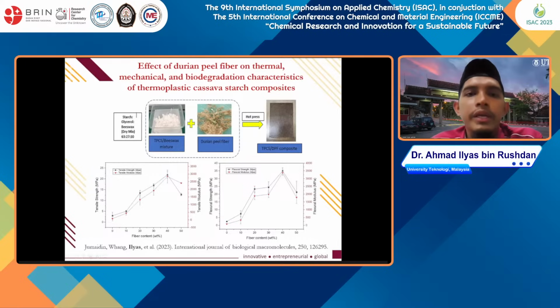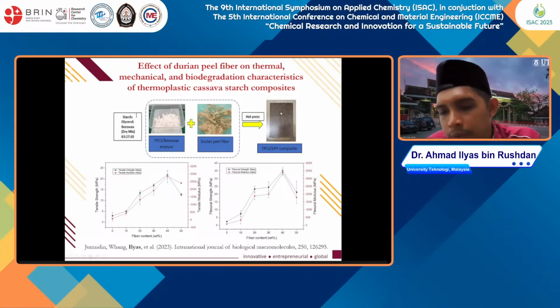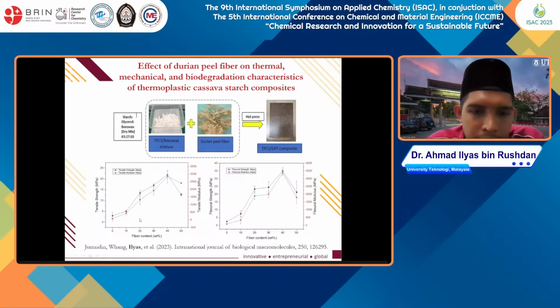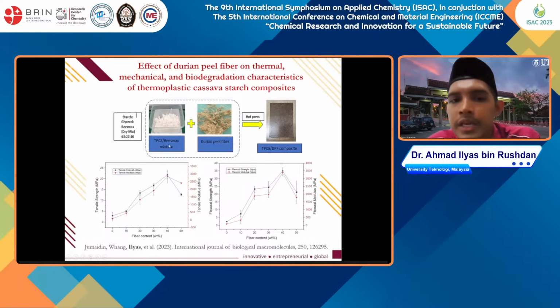This one is using durian fiber reinforced with TPS and beeswax mixture, so we get a rigid structure of the composite. Instead, if we use only the starch, it will give us a film. We can see that when we mix durian fiber with thermoplastic cassava starch and beeswax, the fiber loading is maximum up to 40%, and after that it drops due to agglomeration. This is also the same for the flexural strength.